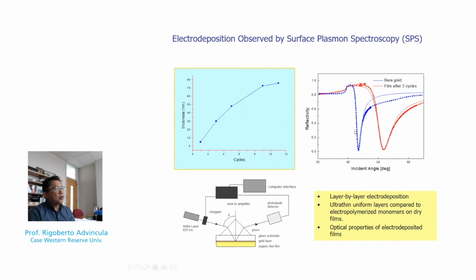In this case, the first use was to investigate the deposition of the films with a variety of thicknesses increasing with each deposition cycle. So as you can see here, as we increase up to 12 cycles, we actually measure the thickness all the way to 75 nanometers. And at 3 cycles, you can easily see here the shift in the Plasmon curve to higher angles, indicating the increase in thickness. Again, using a device like this. So what's important here is SPR was used to monitor the thickness shift per deposition of several cycles of the